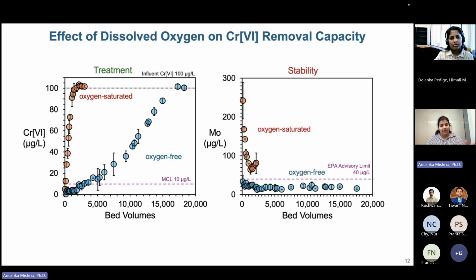Where we probably predict dissolved oxygen to be present in the groundwater. At the same time, when we looked at the stability, we saw that this lack of oxygen actually helped decrease the amount of molybdenum in the water coming out of our columns. So the water coming out of the treatment system had very low concentrations of molybdenum throughout the process, which confirmed our hypothesis that oxygen does interact with the material and is one of the ways the material is destabilized, mostly due to oxidation.